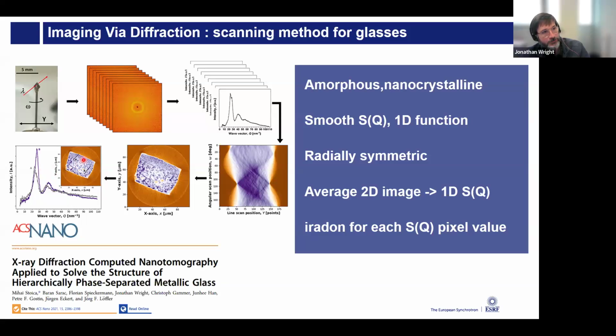And you could scan across and see inside this material, using the X-rays, how you had the phase segregation and how you have obviously different length scales. And you can see which side of the sample was quenched and which side wasn't quenched. And there's, as always, much more detail we could talk about, like what's happening around the little crystals inside of the sample.